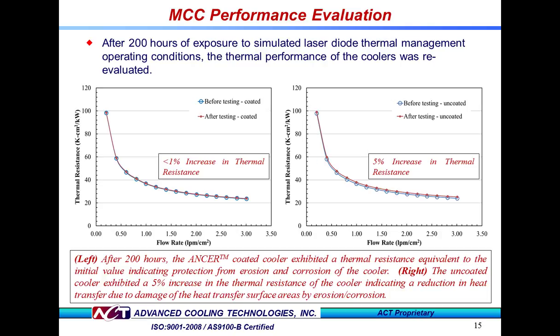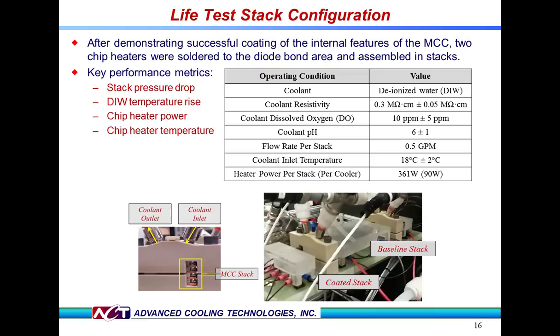Next, we'll reevaluate the thermal performance of the coated and uncoated coolers after the 200-hour test we described in the previous slide. Again, the ANCER-coated sample showed a less than 1% change in thermal resistance after 200 hours. The uncoated sample showed a 5% increase in thermal resistance, a measurable change, particularly when MCC failure is typically determined when the microchannel cooler shows a 20% increase in thermal resistance.